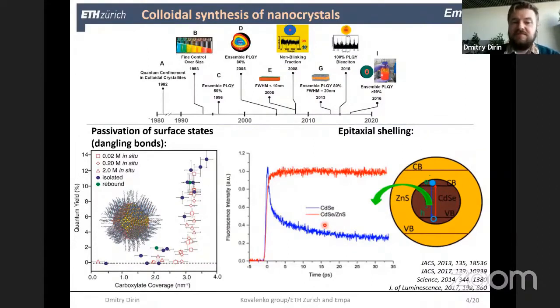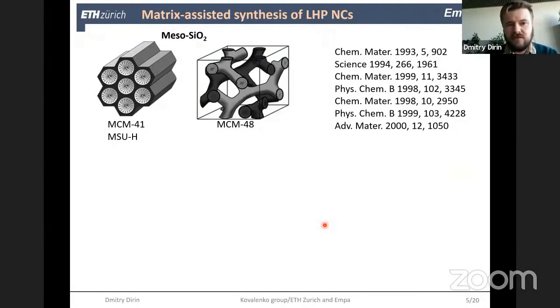So as I mentioned already, because of defect tolerance of lead halide perovskites, this is not crucial anymore. It looks like there were some indications that dangling bonds are not quenching emission. But this was just an indirect indication, predicted by computation, and we wanted to check this in experiment, and there is a very nice model system for that. For a long time, there were attempts to grow nanoparticles inside mesoporous channels of, for example, mesoporous silica.